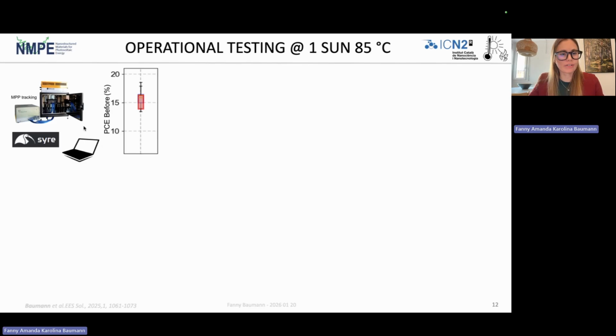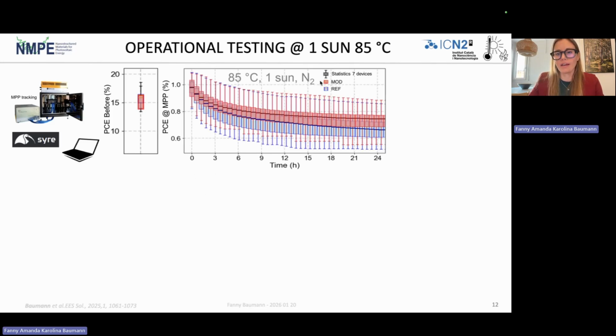For the Litos light operational testing, we see that the initial parallel JV scans show a very similar efficiency in both types of devices. Here you can see the modification in red and the reference in blue. And at 85 degrees, you see that both devices have an initial burn-in, but the profile of the modified devices is much flatter. And this is more apparent in the after JV scans, where we can really see how the modified devices clearly outperform the reference devices. So this confirms what we believe, that the stability enhancement has an effect.